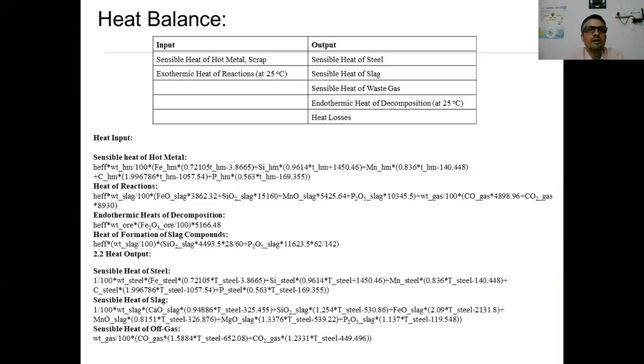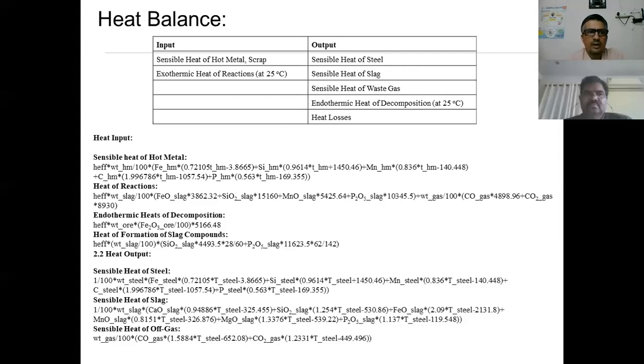That means we require the sensible heat of all the input parameters, the sensible heat of all the output parameters, the exothermic heat of reactions at a standard temperature, and the endothermic heat of reactions at a standard temperature. Similarly, on the output side, there is the uncertain parameter, the heat loss. That means the heat which is lost through the converter lining by conduction, or through the converter mouth by radiation. For that, it is also possible to quantify it if you have the converter dimension and converter design, and then we can develop those models and calculate them.